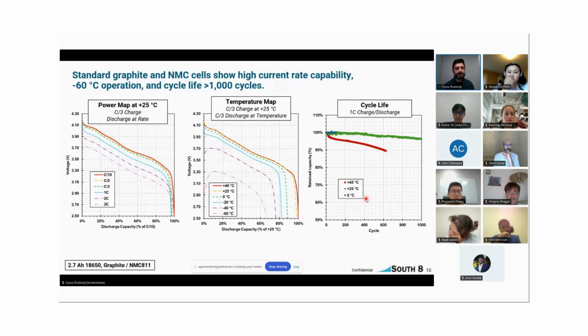Okay, let's get into some data. This is where all the excitement really happens, I'm sure, for a lot of you on the call today. So we want to share some data on this 2.7 amp hour 18650 graphite anode NMC811. So you're run-of-the-mill type lithium ion cell today. Over here on the left, we're showing a power map at room temperature. We charge these cells at a C/3 charge rate and then discharge at various rates from C/10 to 3C.